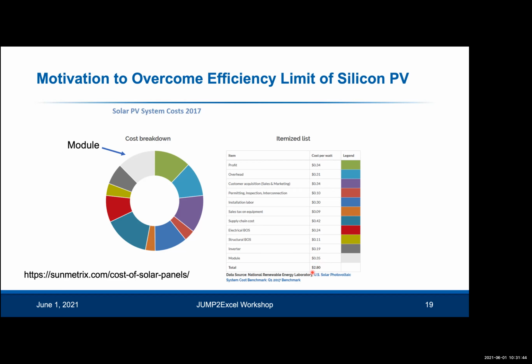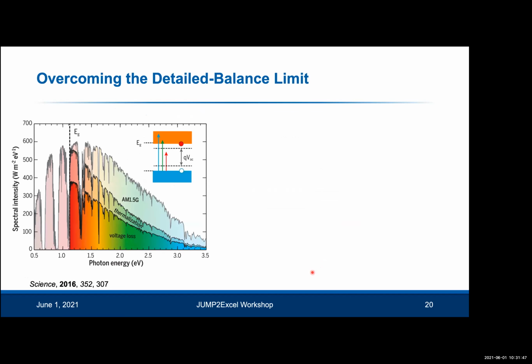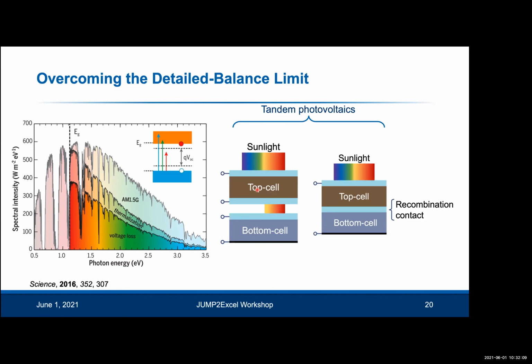And the way in which you can get this substantial increase in efficiency is if you take different solar cells and get them to work together. The reason why you saw that there's a limit to the efficiency that you can get from a single junction device is because there's only one band gap. So you can only absorb light with energy above the band gap, but the energy in excess of the band gap is lost as heat. And if you can bring two solar cells together, then you reduce the energy loss of heat and convert a larger fraction of the solar spectrum into electrical energy.